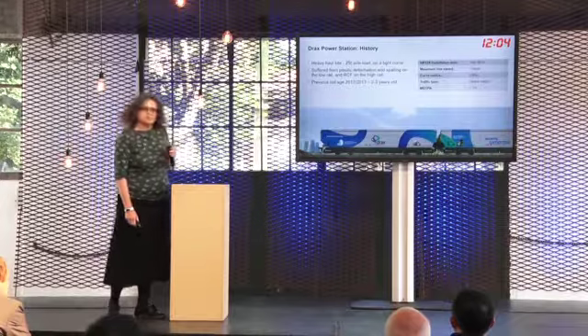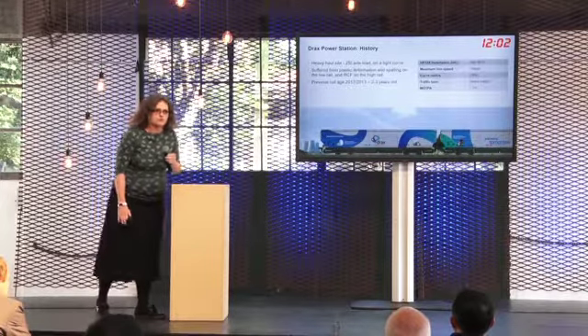So we had some HP335 installed on a heavy haul site. It's at a power station. It's a private site in the UK. It's a 200-metre radius curve. The particular section of track we're measuring has a max line speed of 15 miles per hour. It comes around the curve and has to wait at a signal, so all that weight is on the low rail. So unsurprisingly, it was suffering from low rail plastic flow and low rail rolling contact fatigue.